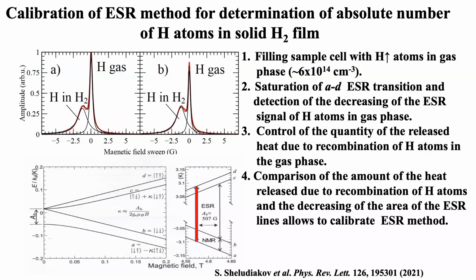And after that, this atom will recombine, because it creates a molecule only when the spins are antiparallel. So this transition leads to the initiation of recombination of the atom in the gas phase. So if we initially register the gas phase, after that we saturate it and measure the heat released during this process.